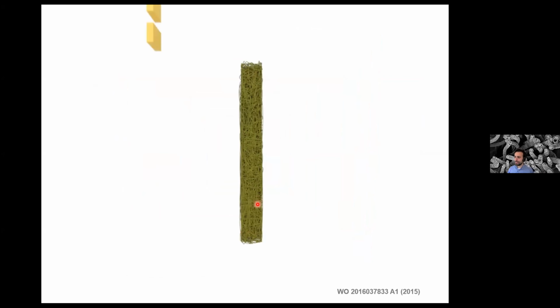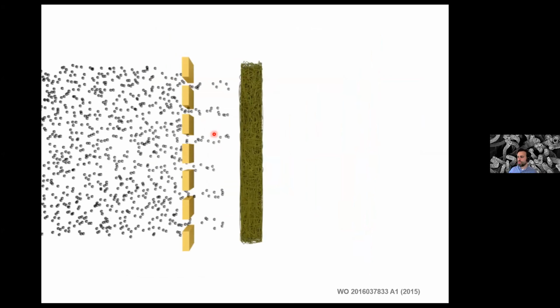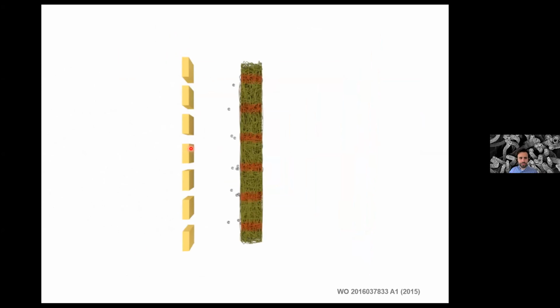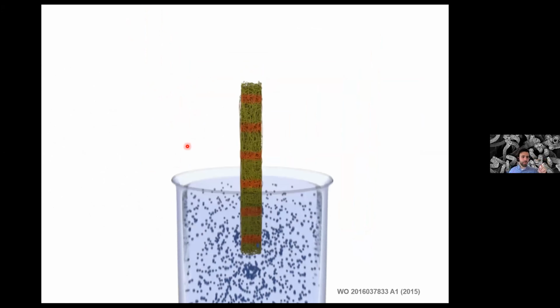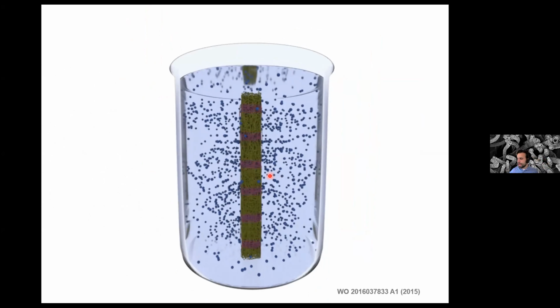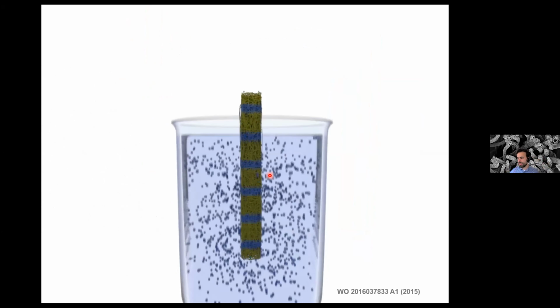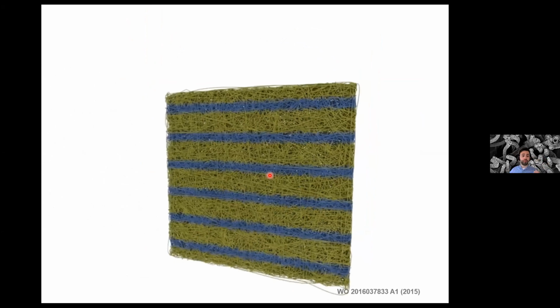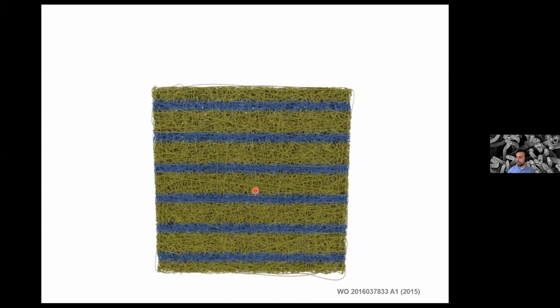And the new step is that we expose these materials to an electron beam using masks that have a predefined pattern so that the radiation can go through some slits. And next to that, we immerse this material in a solution of hydrophilic monomers. And that way you end up having a material that has structured hydrophilic and hydrophobic domains through the entire thickness of the material. And that's why we use electrons, because they have the ability to go through the entire thickness.